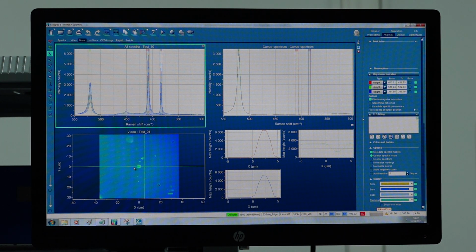That was from one end to the other end. For the silicon peak, as we go into the MoS2 material, as is obvious, the silicon peak will attenuate and will again increase after we have crossed that MoS2 material. Also for the other A1g peak, we can see that as the Raman acquisition reaches the MoS2 flake, the signal intensifies and it again decreases as we move away from the MoS2 material.